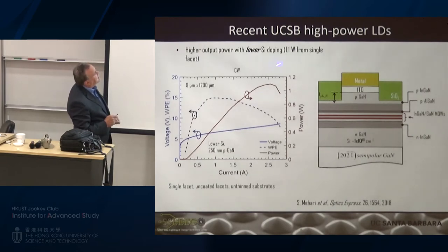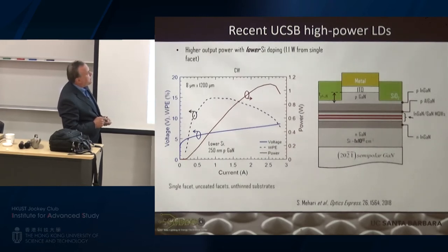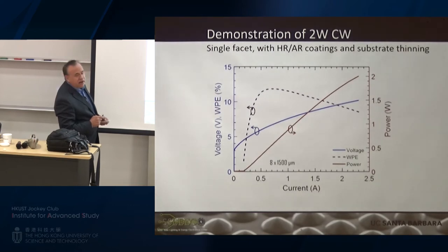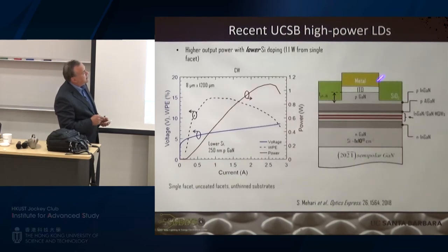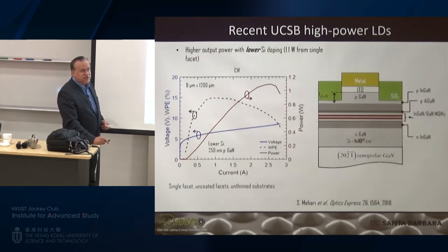This one in particular is one of our first versions. We got 1.1 watt from a single laser facet, but we did some analysis of that. The ITO here is evaporated ITO. In particular, you want it to be very good quality, so sputtered ITO just does not have the quality of the evaporated. This is very thick, 2,000 angstroms. How do you evaporate ITO? E-beam. You could have done co-evaporative sputtering, but that's not as good.